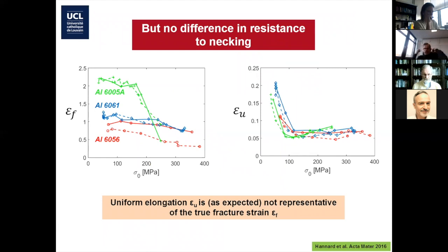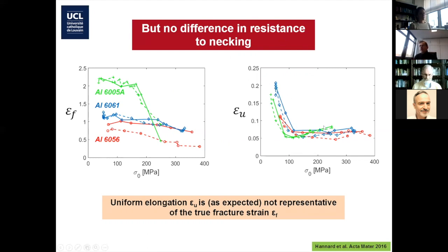Let's try to see if we cannot find an easy answer by looking at the strain hardening capacity. The epsilon_u is the true strain at necking, corresponding to uniform elongation — an indicator of the strain hardening exponent by the Considère criterion. When you compare this curve, the alloys have more or less the same resistance to plastic localization, the same strain hardening capacity. So uniform elongation has nothing to do with the true fracture strain — which is sometimes still a mistake seen in the literature.